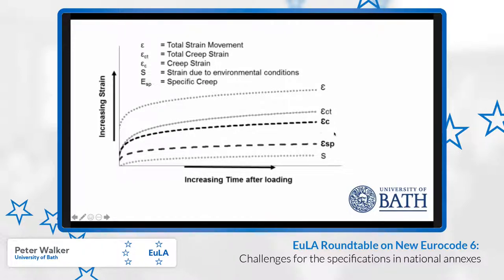And then finally, we were presenting specific creep strain, as shown on the graph. The specific strain is normalized by stress, in the sense that some of our specimens, the mortar specimens in particular presented here, had different stress levels. And obviously, the higher the stress, the more creep strain you might expect. So we have corrected that to give some comparison.